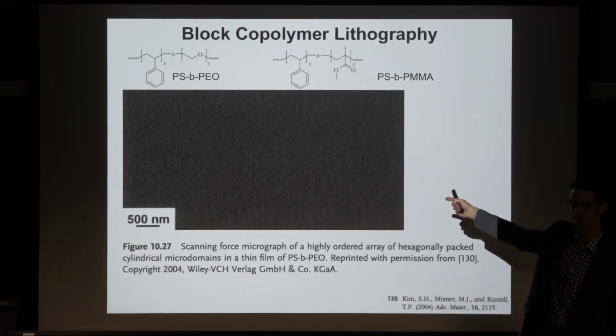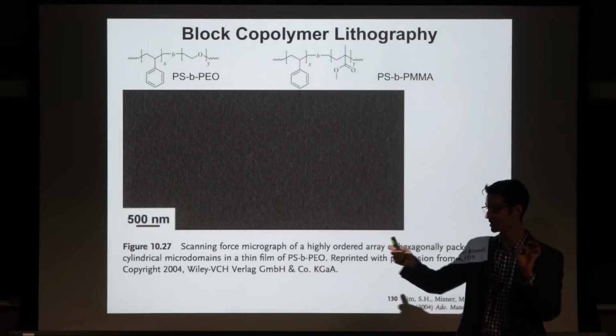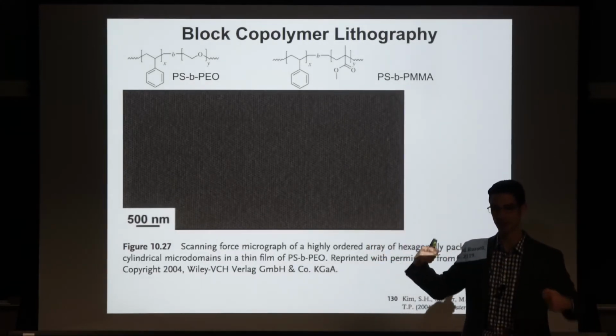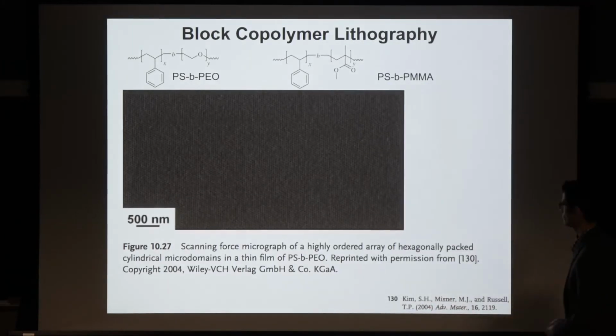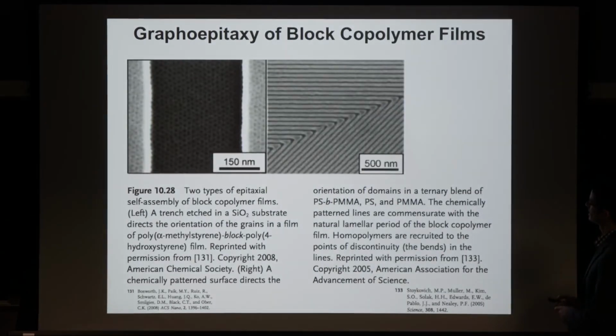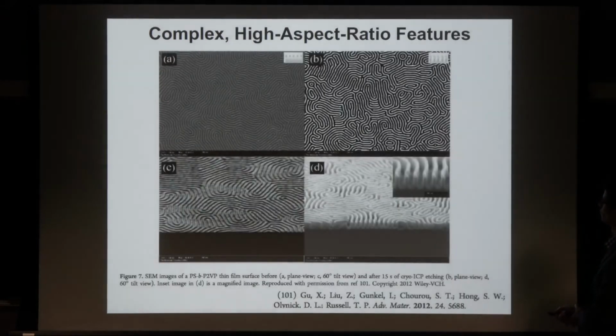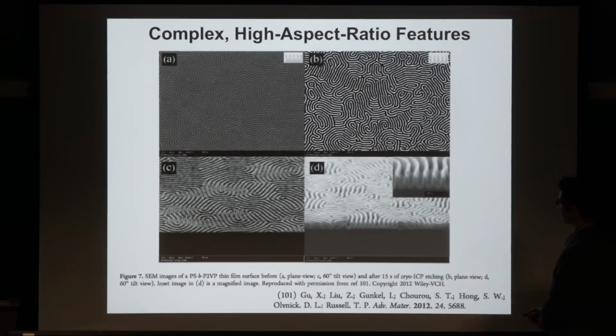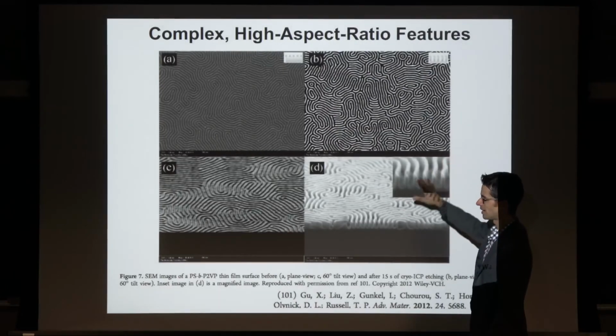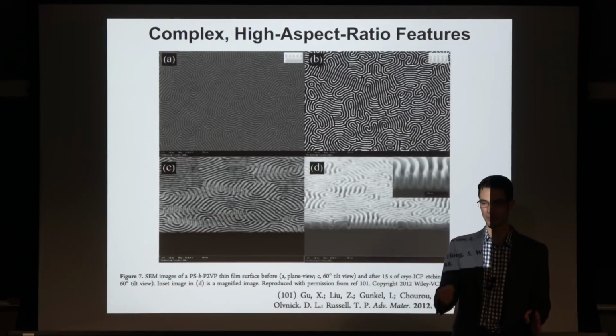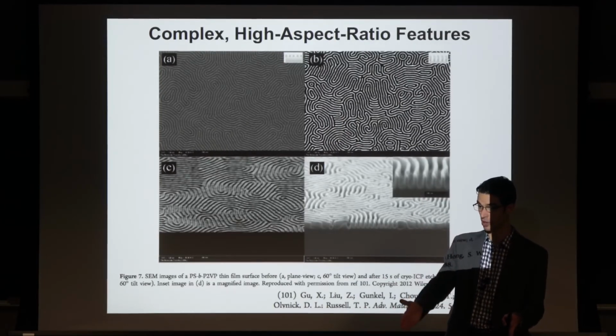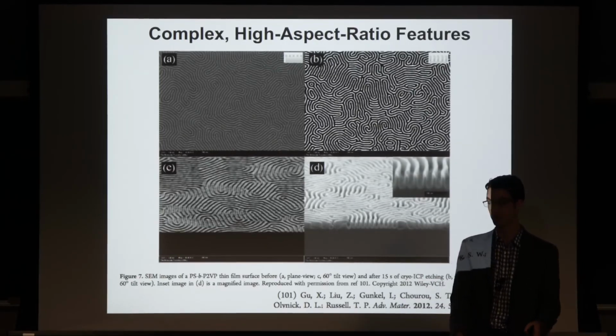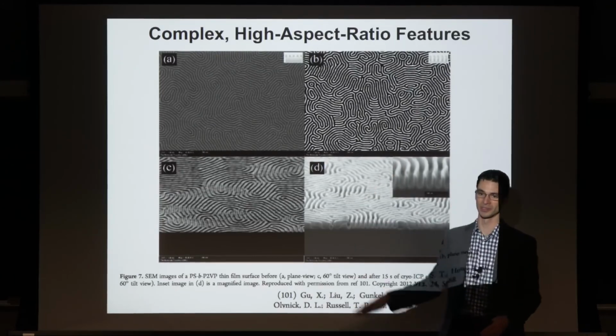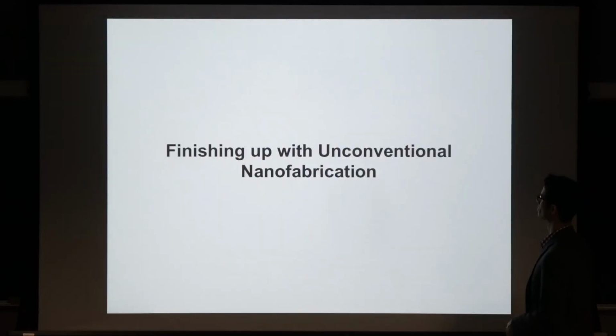You would think that you drew this in a computer, but this is the structure that you get by having polymer chains of precise lengths that don't want to intermix, but they can't get away from each other because they're covalently bound in the center. You can get these things to grow within channels or to bend around curves. This is the lamellar geometry, but it's sideways. You can make kind of cool brain-looking patterns. You can make especially high aspect ratio features, and what's interesting is if you have a photoresist pattern, you can put block copolymers inside it that will self-assemble to be smaller than the features that you can make by photolithography, because the block copolymers have molecular dimensions, and in principle you can make them very small.